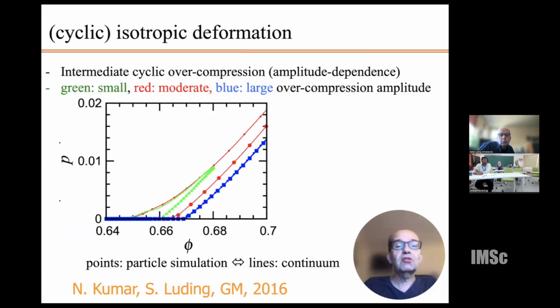Now let's take a look at stress versus density. We come from unjammed, low density, we compress up to a certain magnitude of density or stress, and then we go back. So the green line is going up to density 0.68, volume fraction 0.68, and going back. And this already shows that the jamming density at the beginning, at the loading, is not the same as the unjamming density at unloading. The red is going up to a much higher density and coming back. The red dots, big dots, are the back branch. The small dots are the loading branch. Big dots are unloading. Okay, the amplitude of the difference increases.